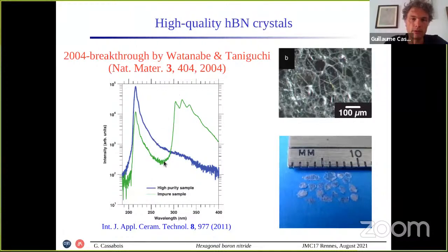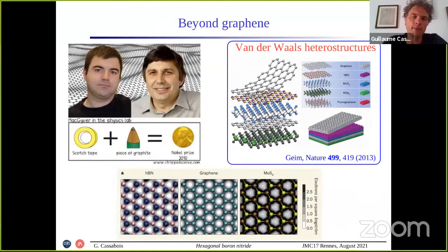Before the work of Taniguchi, the luminescence spectrum was dominated by defects emission around 300 nanometers. Taniguchi managed to grow high quality crystals where the luminescence is basically coming around the band gap with an emission around 200 nanometers, around 6 electron volts. So we are dealing with a kind of insulator, extremely high band gap, around 6 eV, with an intrinsic luminescence around 200 nanometers. These crystals became really important after the advent of graphene.